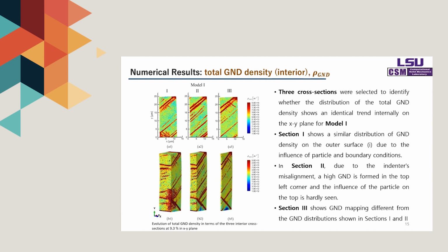Three cross-sections were selected to determine if the distribution of the total GND densities along the outer surface shows an identical trend internally. Section 1 in figure A1 shows a similar distribution of the outer surface of the specimen in the XY plane at the 9.3% strain. This is because the specimen is subjected to the influence of particle and boundary conditions.